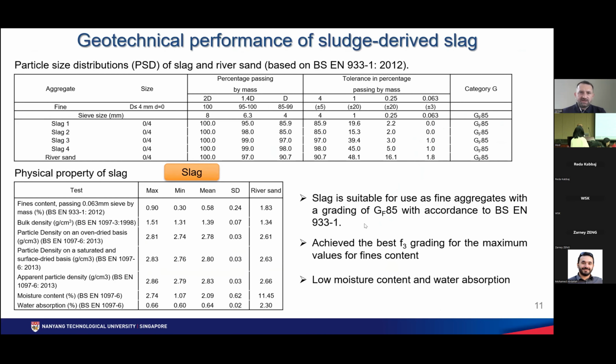Also, we investigated standardized tests for how to categorize slag among the construction materials. And what we found out of the standardized test is that we meet the grading of GF85, which is grading for fine aggregates. So this is exactly what sand is used for in construction. So we can now look at the replacement of sand with new sand or a slag in concrete. This is a big deal because Singapore is one of the biggest importers of sand. So using our domestically developed sand replacement for construction is a big deal.